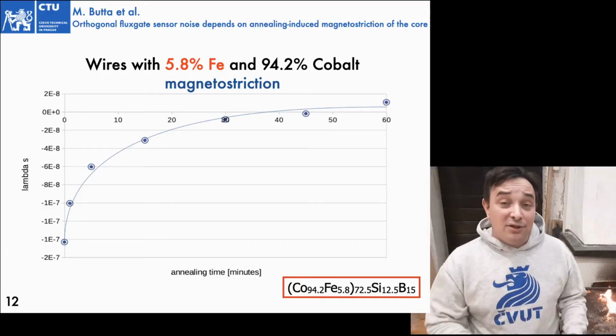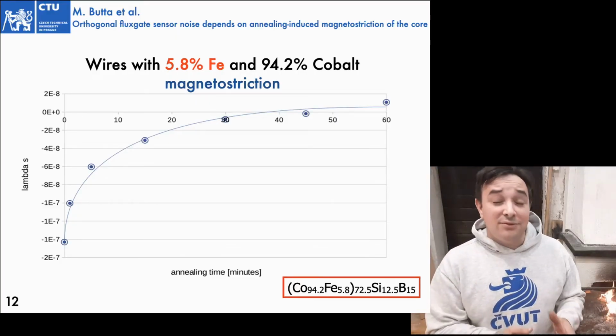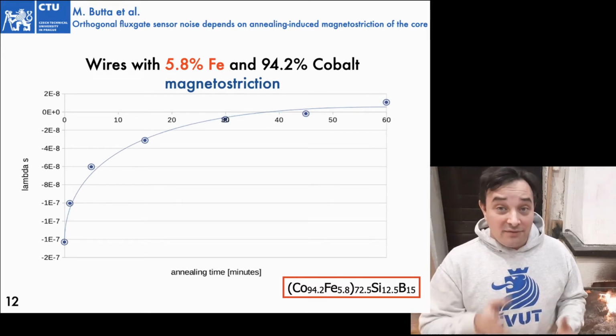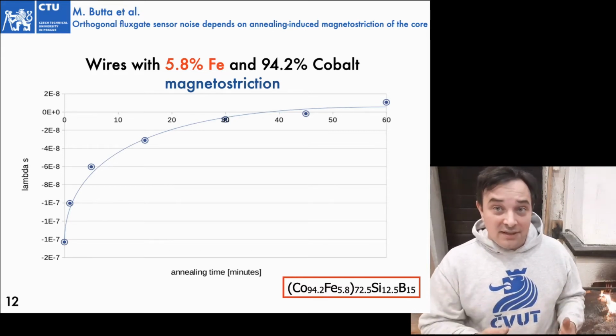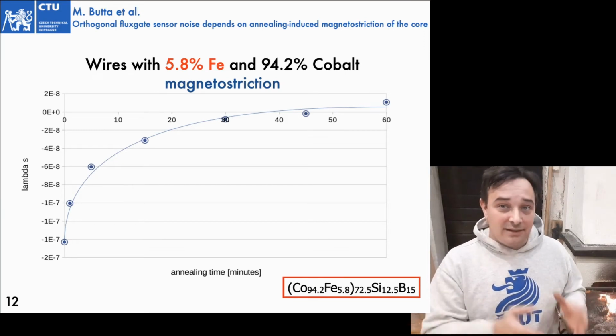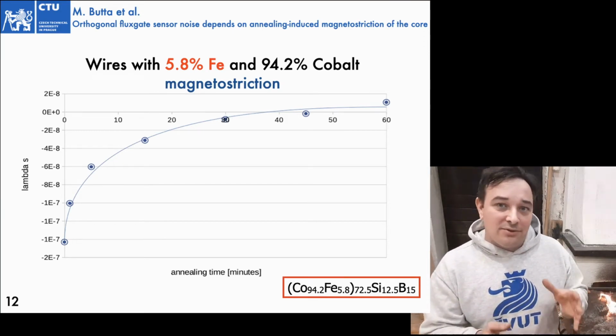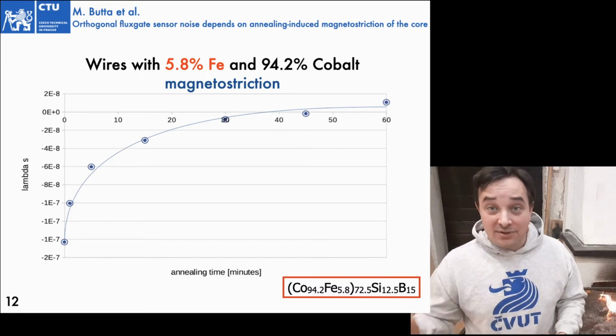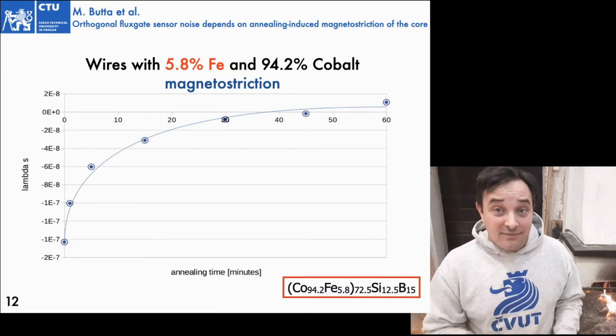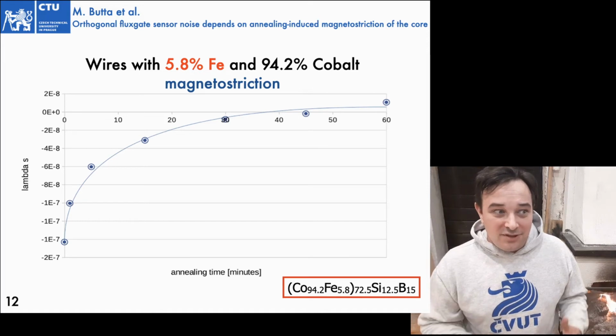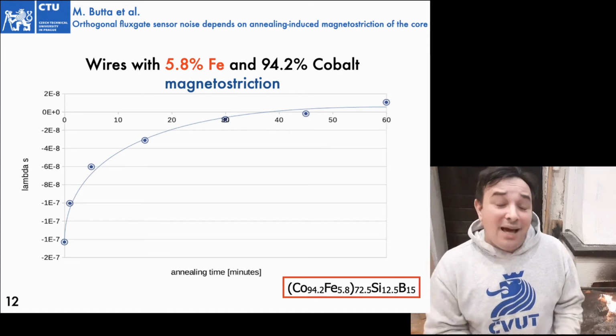So, I tried to create a wire which has 5.8% of iron instead of 6%. So I expect to see a larger negative magnetostriction. And that's actually what I achieved. When I measured the magnetostriction of these magnetic wires with 5.8% iron instead of 6, I get a larger negative magnetostriction. I get 2 10 to the minus 7 instead of 4 10 to the minus 8. So yes, I get a negative magnetostriction which is larger, which is not good because your noise will be larger.